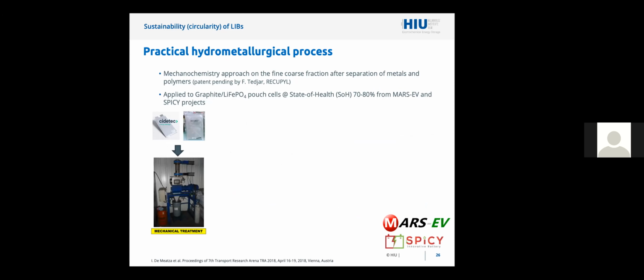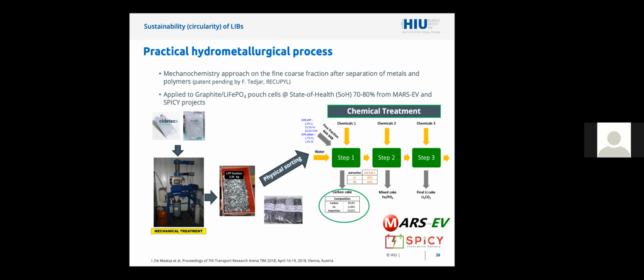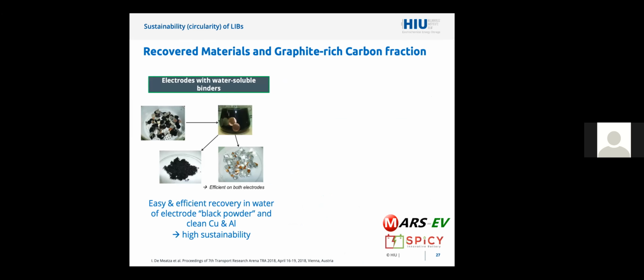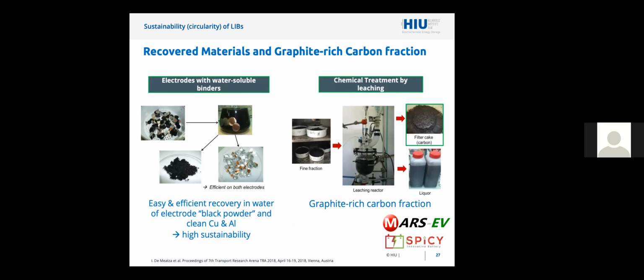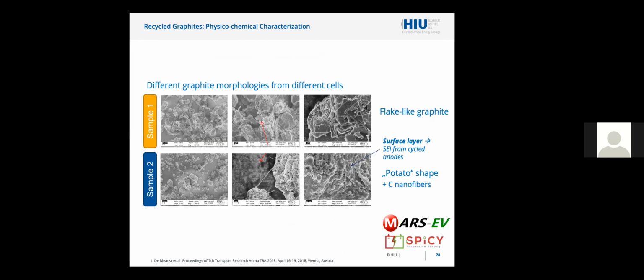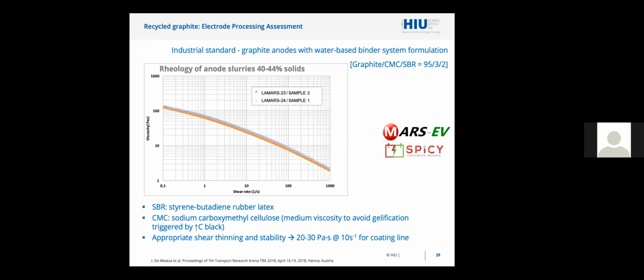What we have been working on is sticking with graphite, where within a couple of EU projects, MarsEV and SPICY, Recupyl developed a process to actually separate everything. And what I'm focusing on today is this carbon cake, only the carbon fraction out of the whole of the crushed cells, which is easy to extract, and this is actually the graphite we could get out of these materials. So, direct recycling of graphite is what I'm talking about. And we have demonstrated that this recycled graphite can be re-employed as it is, without any kind of treatment, for the making of new electrodes.